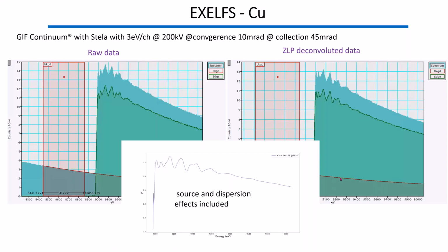Because basically the characteristic scattering angles are much lower compared to the high energy, like 8 keV or 9 keV. So in that sense, you have a bit more mixed information there, I believe, and then it's even harder to get a very proper signal to noise. And this signal to noise I'm talking about is a scattering signal to noise, basically, I guess, but I'm not entirely sure about that. We haven't tried that. It's just my guess.